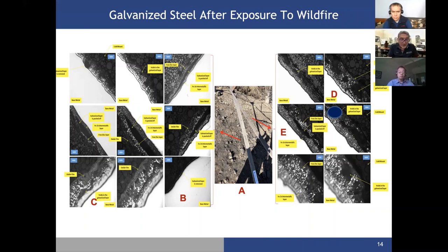If you look at the picture identified as C on the left side, you see evidence of extreme formation of oxides on the surface of galvanized steel. Picture D on the right-hand side on top shows presence of big, large voids in this galvanized layer. And picture E shows delamination of the galvanized layer. All of them indicate there is no more corrosion protection on this material due to confined areas where zinc has been affected, oxidized, delaminated, or doesn't exist anymore.